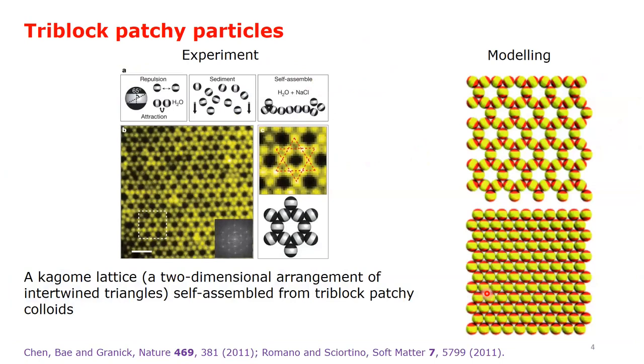The Granick group provided a major breakthrough in self-assembling colloidal open crystals about 10 years back. A Kagome lattice was self-assembled from tri-block patchy particles in a quasi two-dimensional system. Note that this is a Maxwellian lattice in 2D.